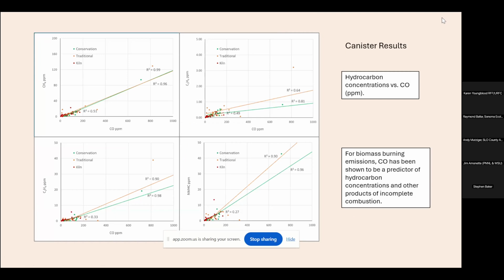Okay, so these are the results from the canister analysis. These are in concentrations, and from very many studies of wildfire emissions, it's been determined that CO, which is a product of inefficient combustion, correlates very highly with almost every other product of inefficient combustion, VOCs and other hydrocarbons. That's what we found for this study. You can see our R-squareds between CO and some of these other hydrocarbons, some C2 and C3 hydrocarbons, was pretty high.